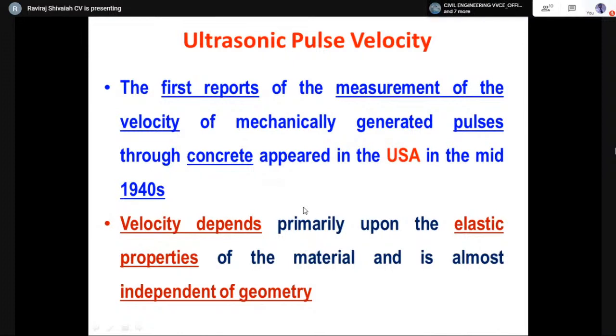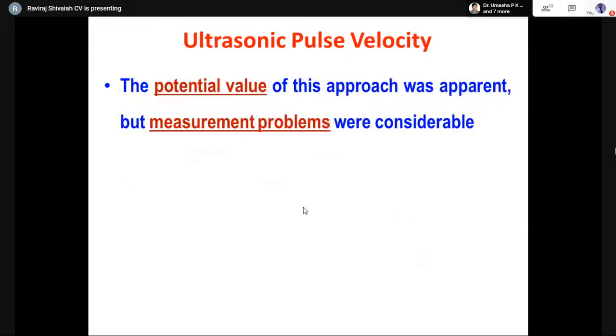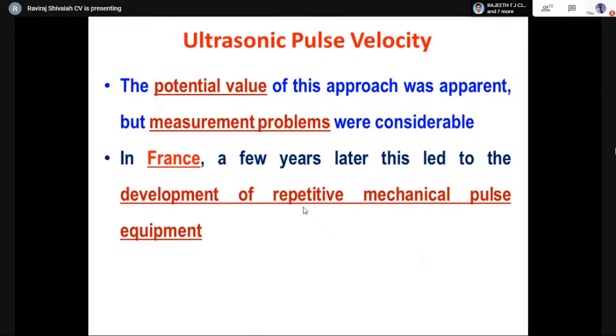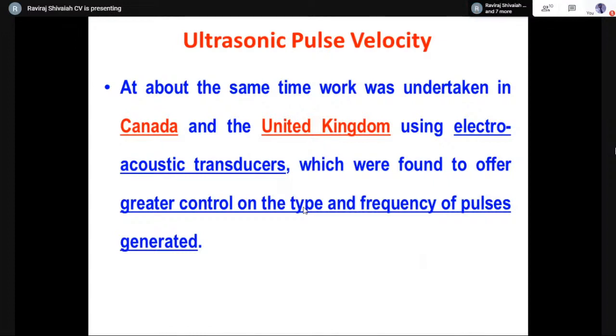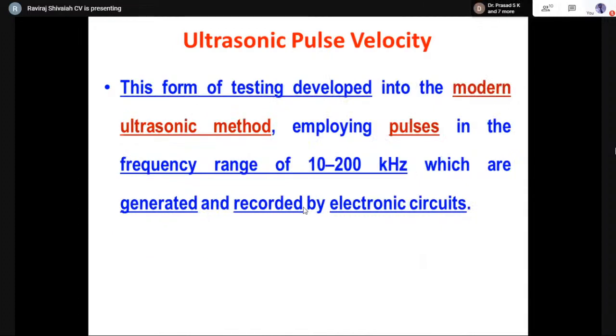And this clearly showed that velocity primarily depends on elastic properties and not on the geometry of that particular member. This was a very important, interesting observation made in the 1940s, which led to the evolution of the ultrasonic pulse velocity method. But at that point of time, the major problem was how to measure this accurately, because they didn't have the means and ways to measure the velocity appropriately. So a lot of research happened in France, Canada, and the UK, where people tried to develop very good electroacoustic transducers, which had good control on the type and frequency of the pulses generated.